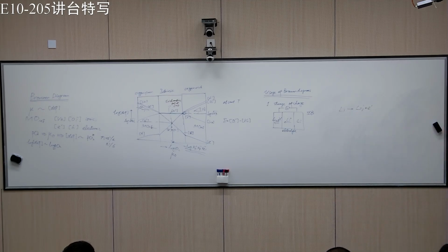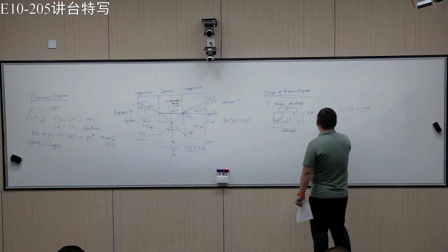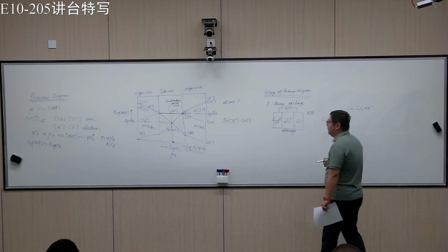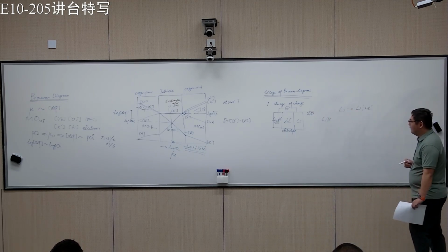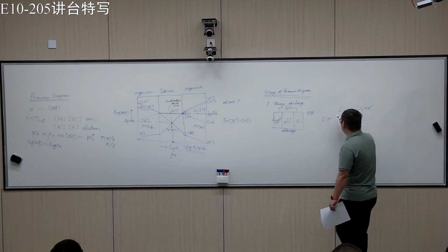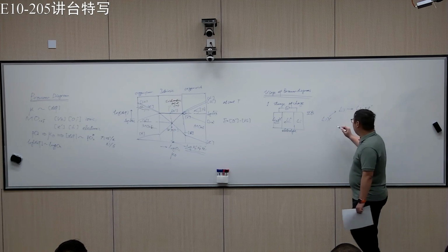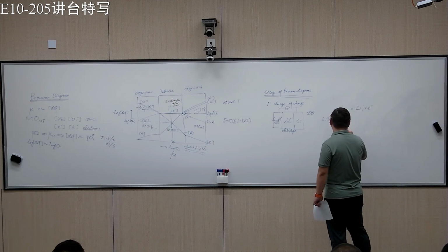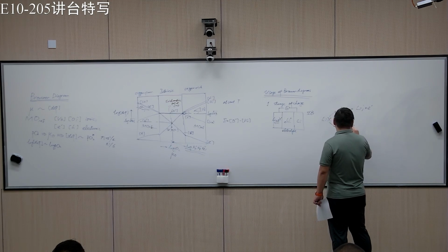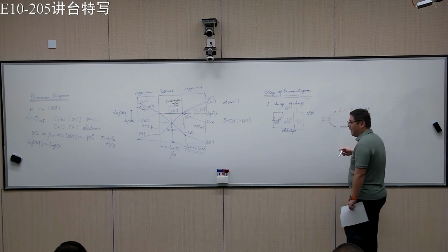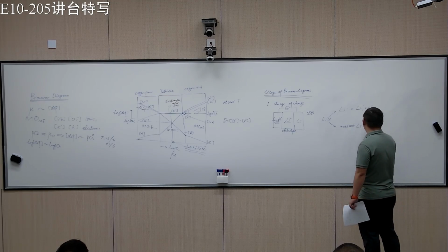Of course, you can also remove lithium. If you start with stoichiometric lithium X, then you start to change the stoichiometry. You can either put more lithium into the structure, or you can remove lithium. If you take out lithium, you are left with lithium vacancies and holes.